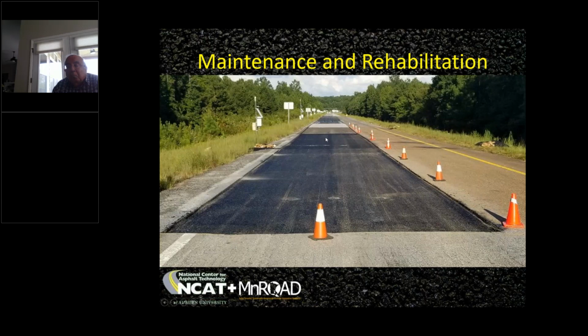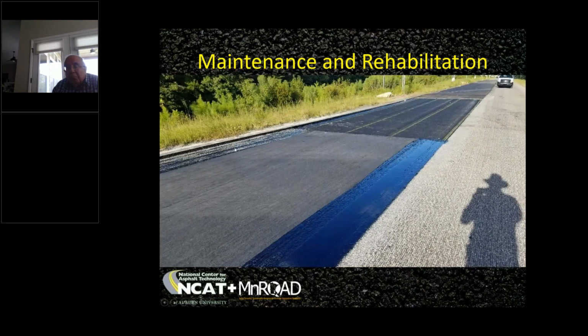These 2 are chip seals. This is a coarse fractionated wrap chip seal. That's a virgin number 7 granite chip seal. And then down at the far end, this is a geosynthetic fabric, and this is a geogrid in combination with a non-woven fabric. In all 6 of these sections, there are cracks underneath that we map. They're identical cracks in all 6. So what we're looking for is the recurrence of cracking, so that we can report to Georgia DOT, which is a sponsor of this, but because Missouri is a partner in the study, they also get the benefit of the results and implementation support.